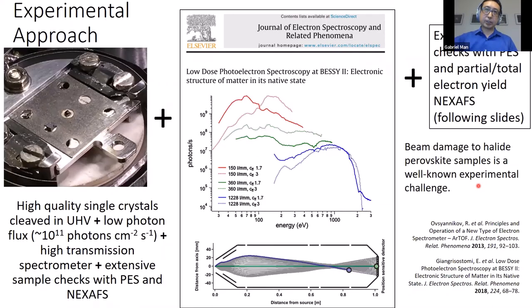The approach I've taken here is to start off with high quality single crystals of halide perovskites supplied by Dr. Prabhu Nayak, then cleave them in UHV, then measure on them using a low photon flux beamline, which is roughly 10 to the 11 photons per square centimeter per second. To compensate for the lower flux, we have to use a higher transmission spectrometer. Here is a schematic of the ArTOF spectrometer, which is just a giant flight tube. And to ensure that we know what we're measuring, I've developed a protocol to check extensively for beam damage, using a combination of photoelectron spectroscopy and more surface sensitive or bulk sensitive NEXAFS.